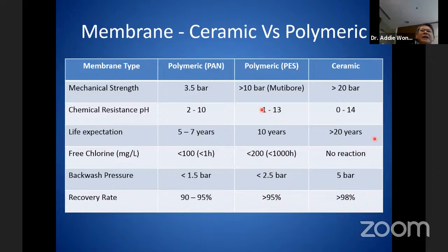Polymeric, it depends. PES can now go for 10 years or slightly more. For chlorine resistance, you can see this one is less than 100 ppm for 1 hour, this one is less than 200 ppm for 1,000 hours. For ceramic membrane there's no reaction, which means you can continue to dose oxidant and filter, no problem.